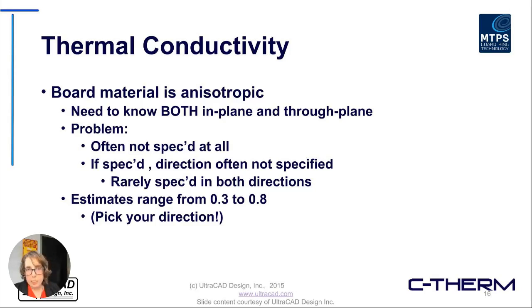So the challenge is that the thermal conductivity on these boards is often not specified by suppliers, or if it is specified, it's not specified according to the direction. It's just a single number is given, and you have to assume it's isotropic, even though you know it's not. Estimates available in the literature range from a worst case scenario of about 0.3 watt per meter Kelvin up to about 0.8 watt per meter Kelvin. So that's a pretty wide range. It's greater than a factor of 2. And it introduces a lot of uncertainty into numerical modeling.